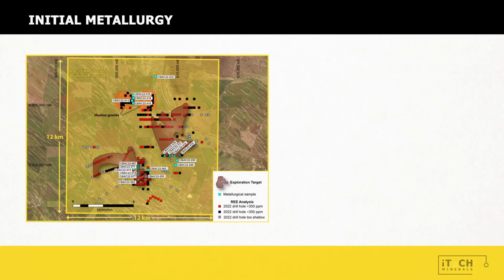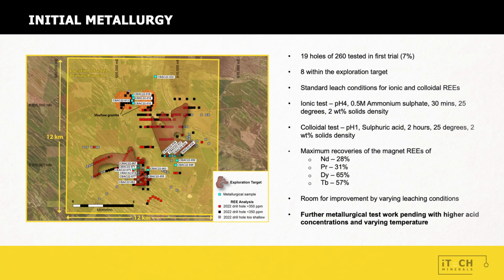So the initial metallurgical test work that we did, we tested about 19 holes out of the 260 holes tested. So that's about 7% of the holes that we drilled so far, and 8 of those are within the current exploration target. So what we did was use very standard leach conditions for both ionic and colloidal rare earth elements. So the maximum recoveries that we achieved for neodymium and praseodymium were between 28 to 31%, and for dysprosium and terbium it was between 57 and 65%.